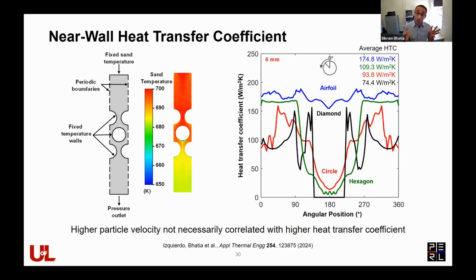It promotes really a collisional flow, where the particles move much more uniformly around the coupon, whereas all these other geometries had streaming flow, where you had blockages in some parts and free flow in other regions of these coupons. So that is what we think explains the higher heat transfer coefficient of the airfoil relative to these other geometries.